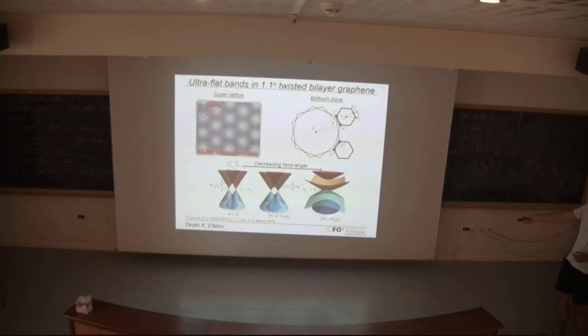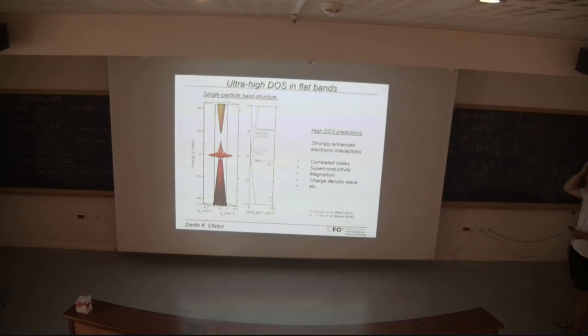Just to explain this band structure a little bit better, this is the single particle band structure. All of this is single particle for now, so there are no interactions in the game yet. This was first calculated by Bistritzer and MacDonald, and also derived in Pablo's Nature paper. If you look at the band structure at the magic angle, at the energy in K-space, you can see that the band structure is completely renormalized, and you get these ultra-flat bands at around energy 0. These flat bands are very, very flat in the sense that their bandwidth is only on the order of 10 millielectron volts. So these are extremely narrow bands.